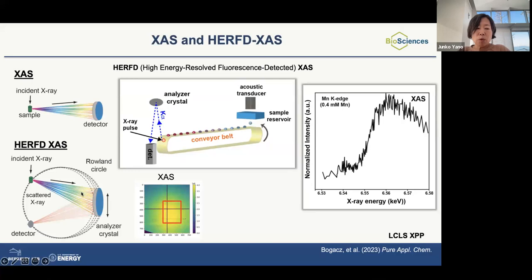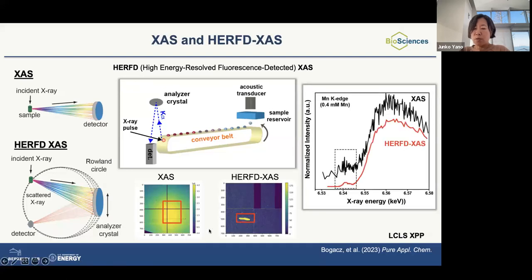But we did one more method. One is HERFD-XAS, high energy resolution fluorescence detected X-ray absorption spectroscopy, using analyzer crystals. In this case, we used the K-alpha crystal, using Bragg reflection to select the K-alpha signal from manganese. That way, we can reduce the background quite a bit. Probably the fluorescence signal is also reduced, but the reduction of background is significant.